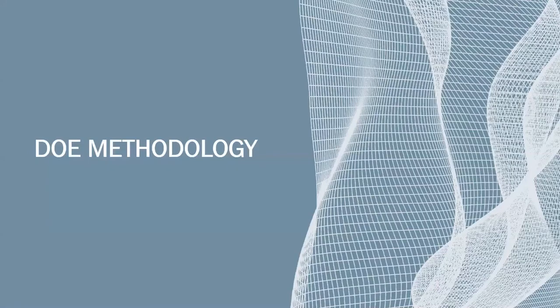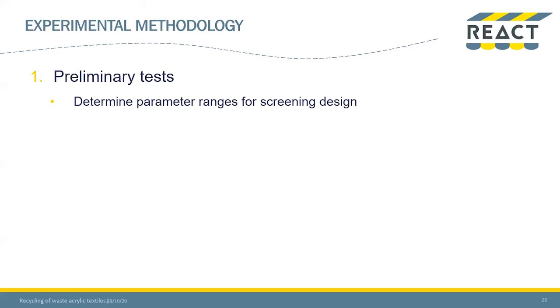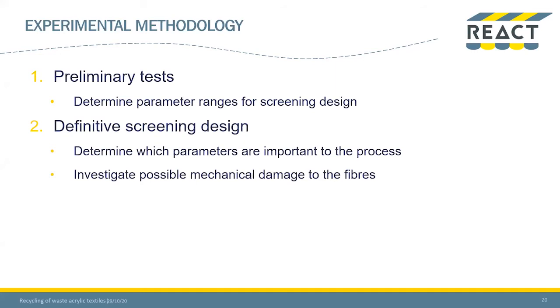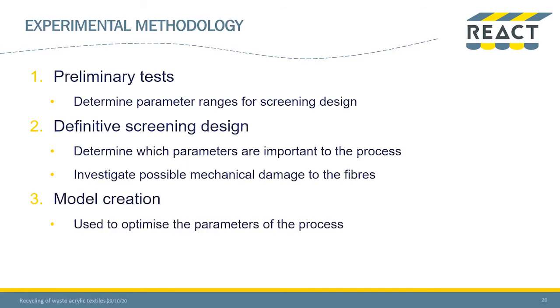And then to execute our experiments, we used a design of experiment methodology. First of all, we did preliminary tests to define the parameters we wanted to evaluate and their range for a screening design. These parameters were defined based on literature, but also on lab trials. Then via a definitive screening design, we could determine which parameters are important to the removal process. And we investigated as well in this step the mechanical damage to the fibers. And these results then allowed us to create a model which allowed us to optimize the parameters of the process and to finally perform optimized tests.